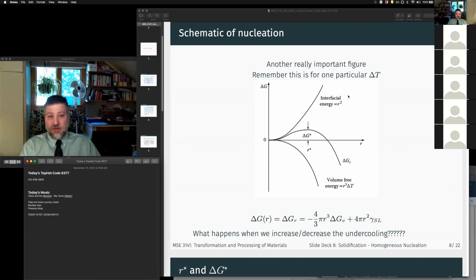And we remember from the Gibbs-Thompson effect that the system with the interface is going to have a higher Gibbs free energy than that without, and that the penalty that we have to pay per unit volume of our secondary phase is proportionally greater the smaller the radius, because the surface area to volume ratio is higher, right?